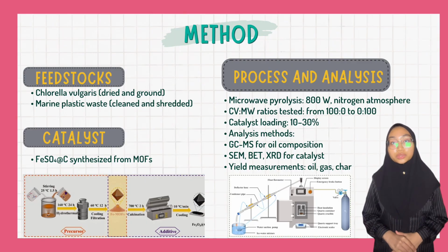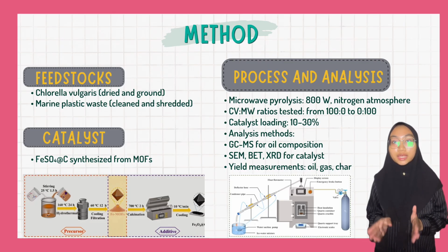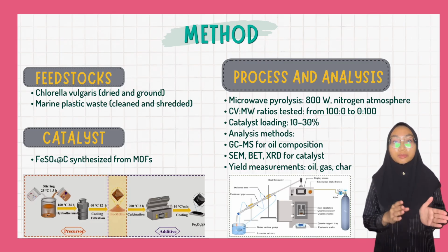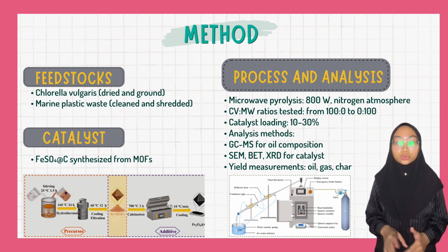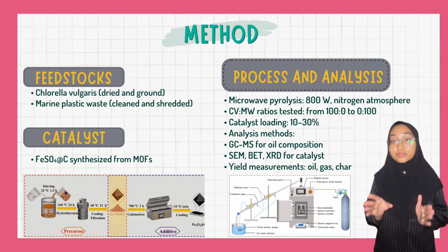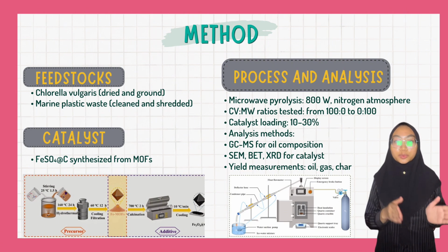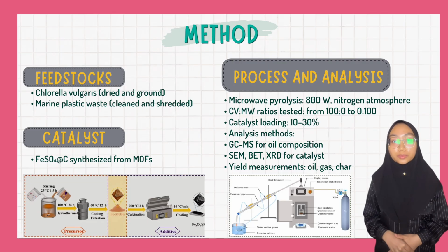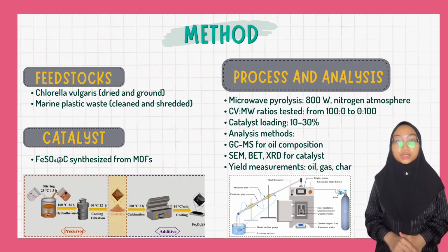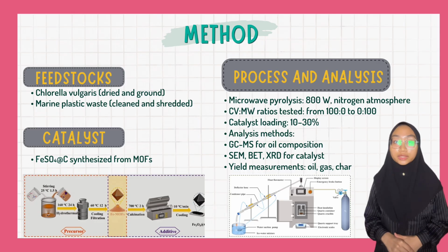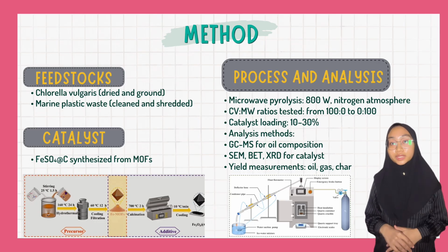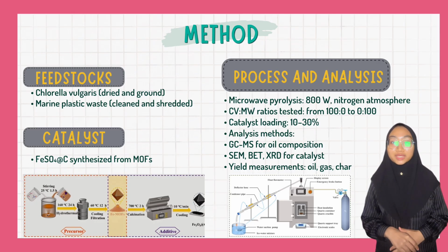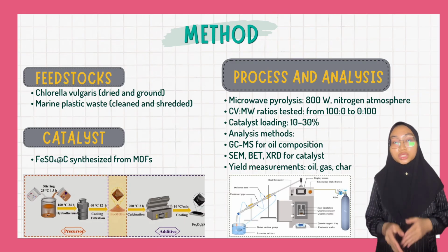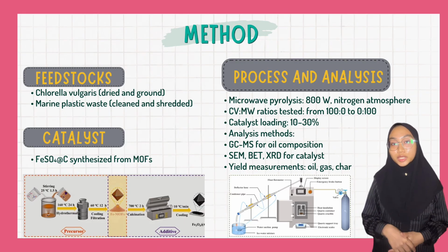We also measured the yields of oil, char, and gas. The oil quality was analyzed using GCMS, and we used SEM, BET, and XRD to study the catalyst structure and performance. The preparation process was very important. We had to ensure the algae was properly dried and ground to ensure uniform heating, and the plastic was cleaned to avoid contamination that could affect oil quality.